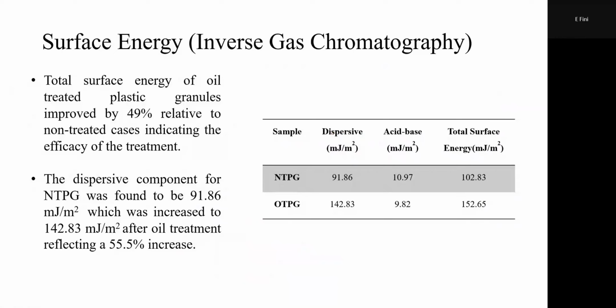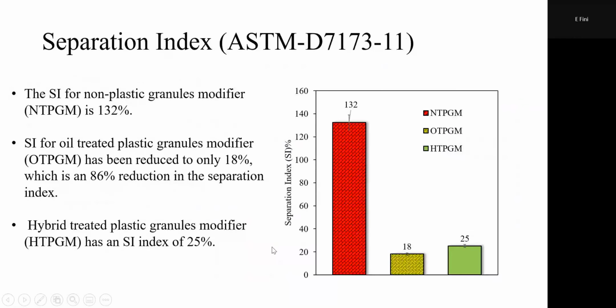The whole reason we wanted to make it compatible to begin with is so we want the interaction to be higher. So in this case, when we went from 91 to 142, that's a significant increase in surface energy. Now we want to know: does it really interact better with its surroundings now that we changed the surface? So with these three tests, we proved that what we did changed the surface, changed the plastic, even though the color did not change. So now let's see if it helps.